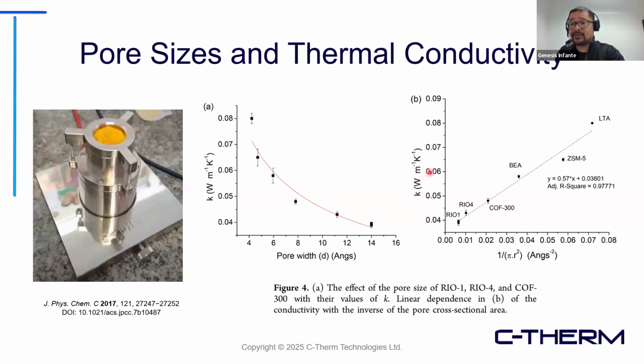So diving into very specific examples on how the MTPS can give this information about MOFs when it comes to its thermal properties, specifically conductivity, is this example right here, published in 2017. You can see that they have their material on top of the sensor right here within this special container. And what they've figured out is that there is a direct correlation between pore sizes and essentially the thermal conductivity of the MOF material. So there's a trend where the pore structure and geometry really have that direct impact, and you can see that if you map out the correlation between thermal conductivity versus the